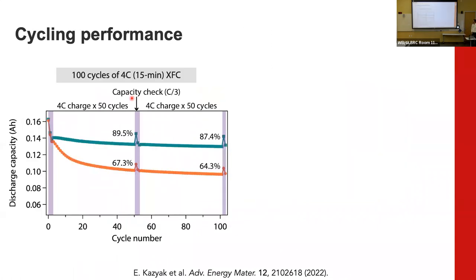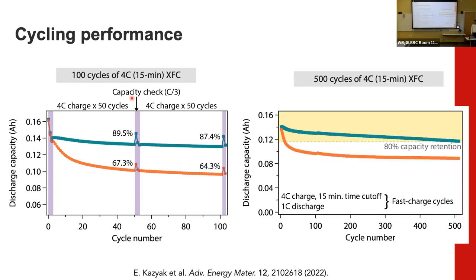As a result, our cells retain a lot more capacity than the control. The control is in orange in this case, and the ALD is in that blue-green. And we can still cycle out to that 500 cycle number while retaining 80% capacity, which is kind of a common failure metric in batteries.